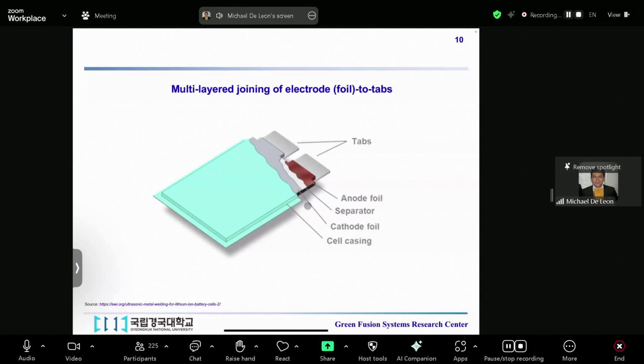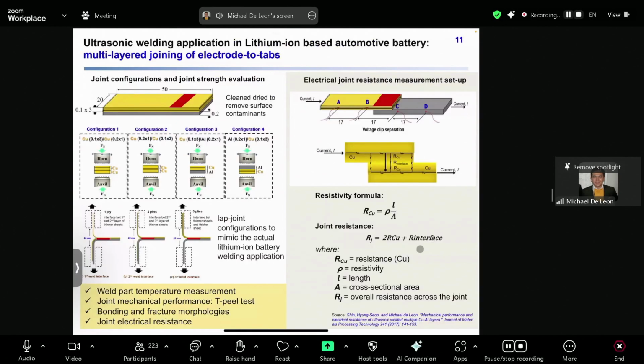Electric performance, on the other hand, was equally crucial. We used a four-point method with copper terminal blocks located at both ends and precisely placed voltage clips. We calculated the total joint resistance as the sum of the bulk copper resistance and the interface contact resistance. This setup lets us isolate the key advantage of UW, since it eliminates the solder-related resistance.